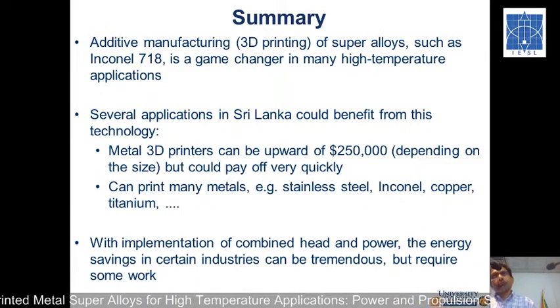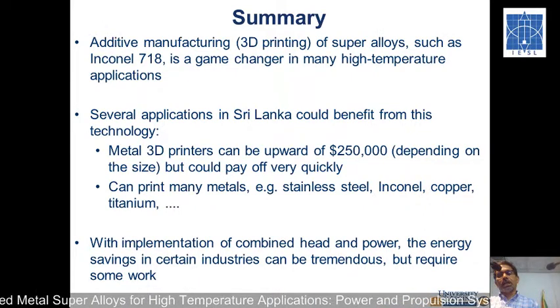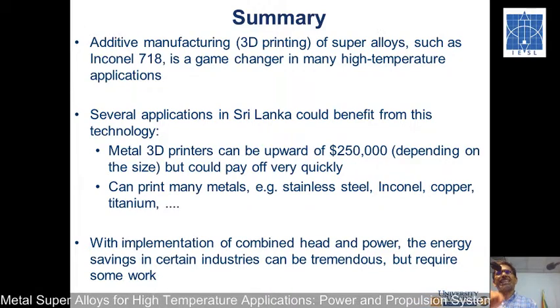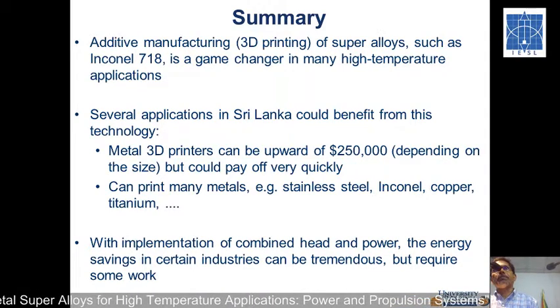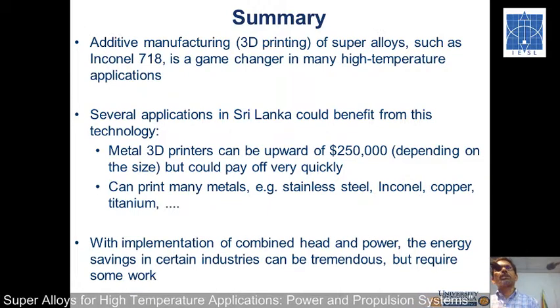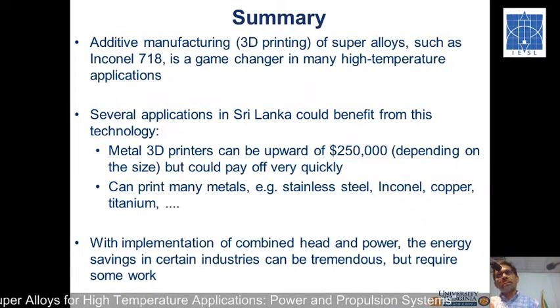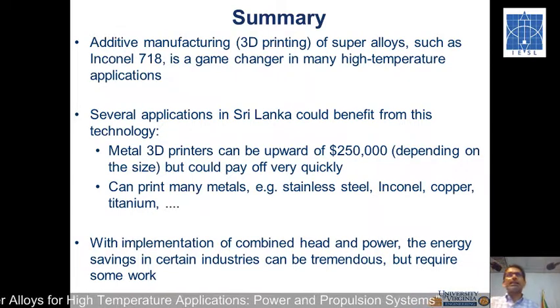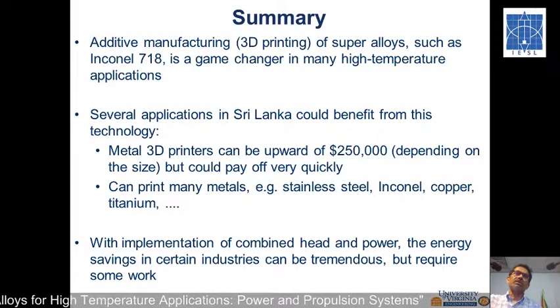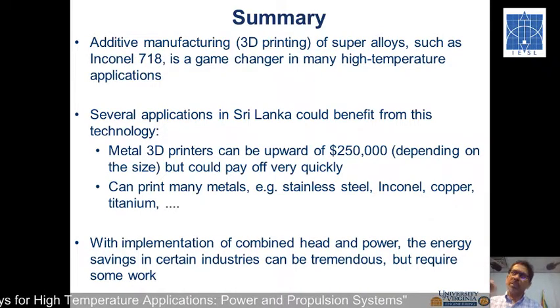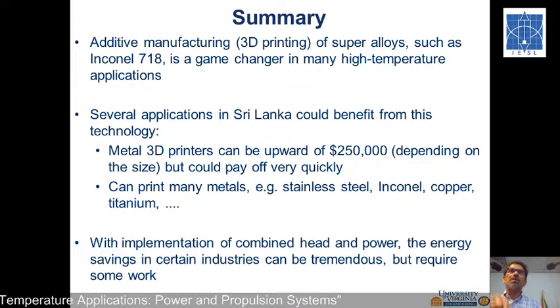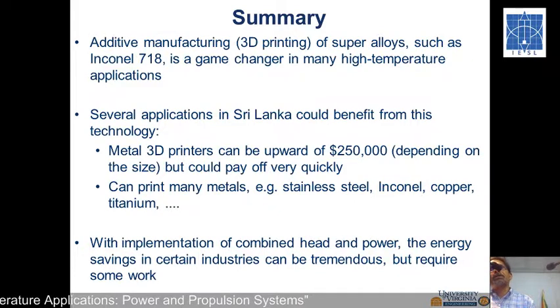You first lay one layer, and then the laser will go and melt it. It's called selective laser melting, SLM. That's the standard sintering kind of process. Once one layer is done, we apply another coating of powder. I don't know exactly the thickness of the layer, maybe it could be 100 microns. The laser will again selectively heat based on your design. So you build layer by layer, essentially sintering it.